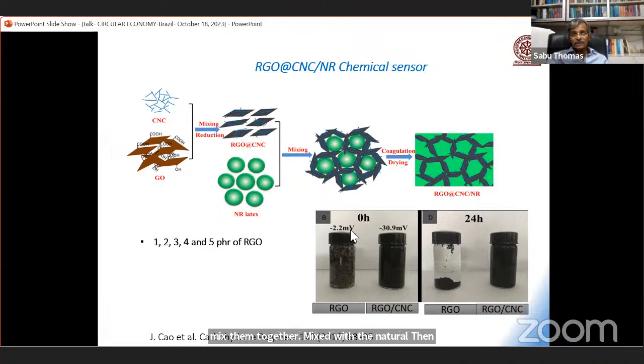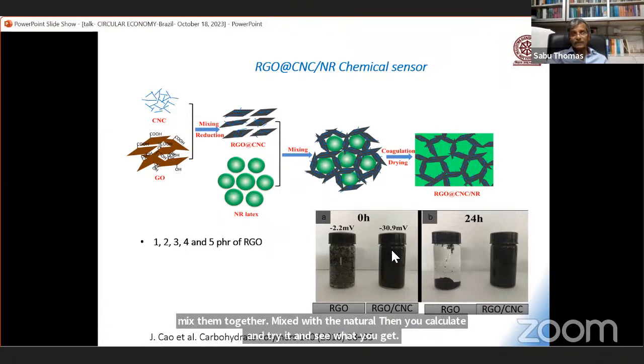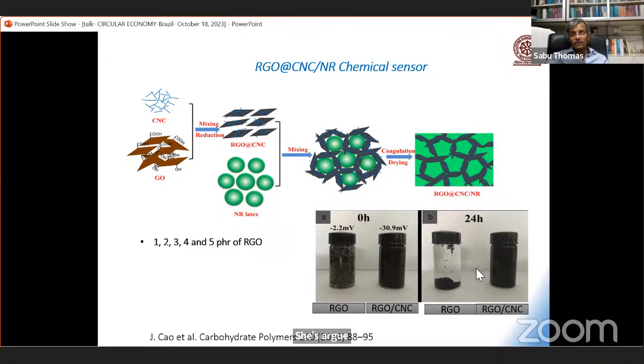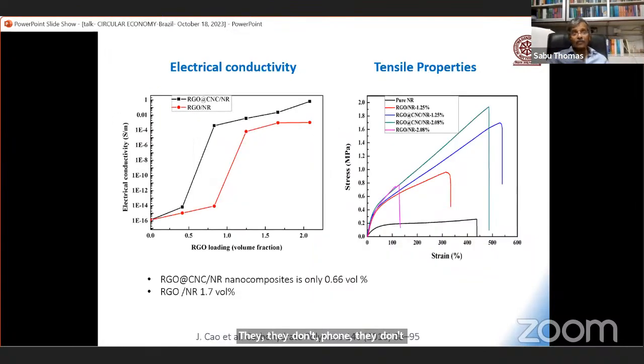You see what you get. This is RGO. This is RGO CNC. 0 hour. After 24 hours, if you keep it, you see all the RGO is settled. But look at RGO CNC is extremely stable. So my point is, when you mix RGO and nanocellulose together, the dispersion becomes more efficient because the RGO interactions could be suppressed. They don't undergo any agglomeration. And now I want to show you the percolation process. If you use RGO alone, reduced graphene oxide alone, you see the percolation process beyond 0.5, 0.75.